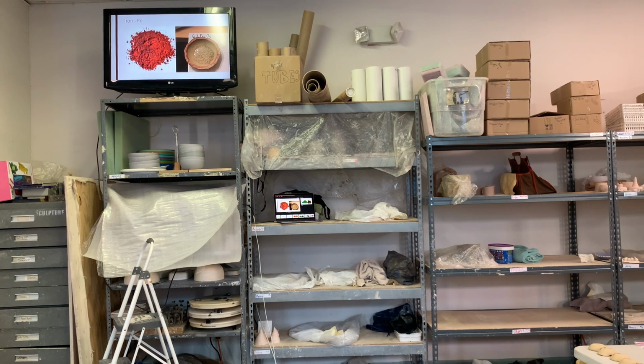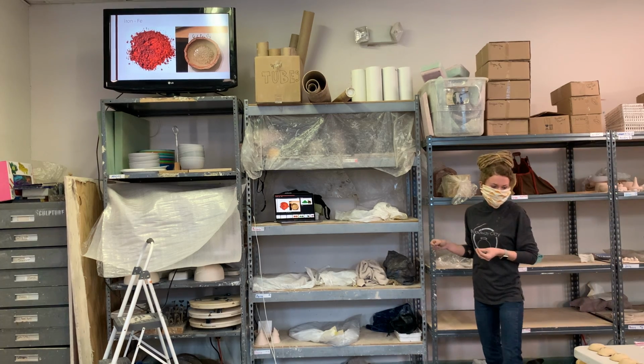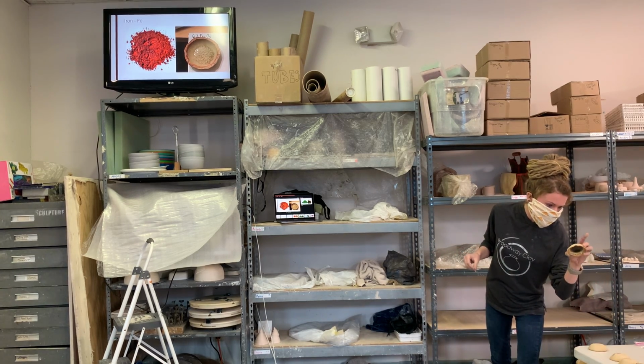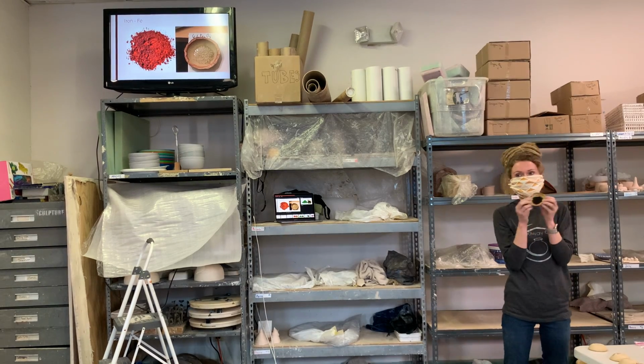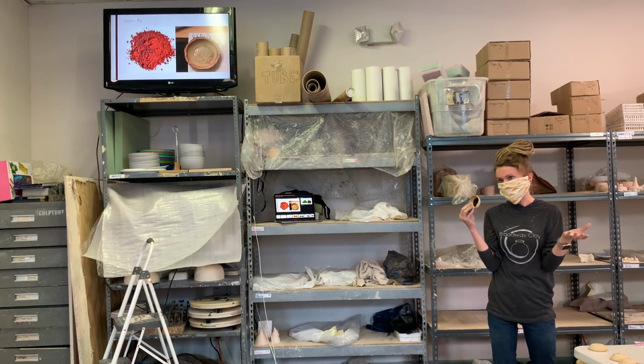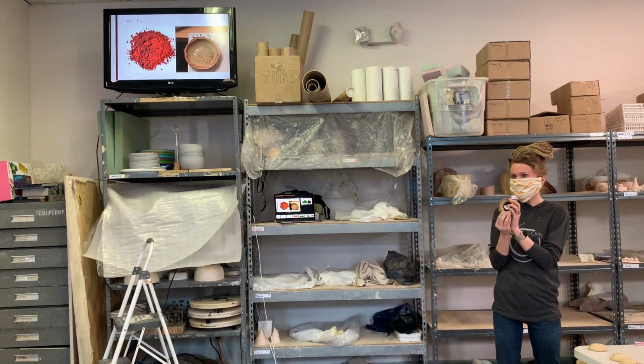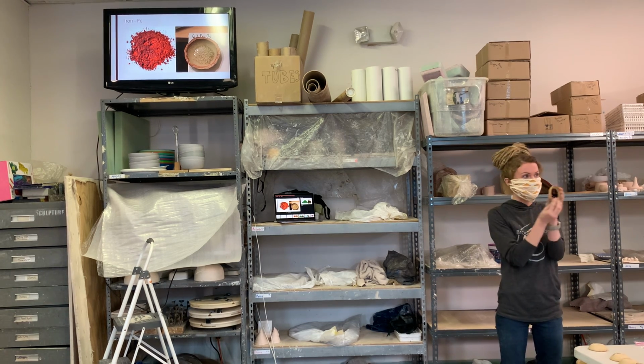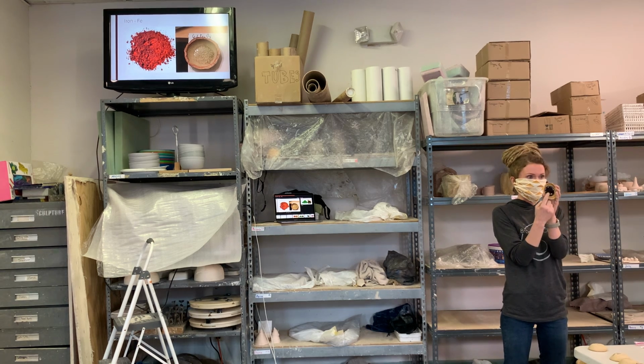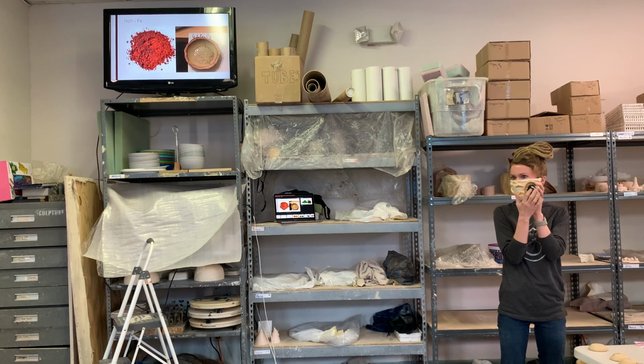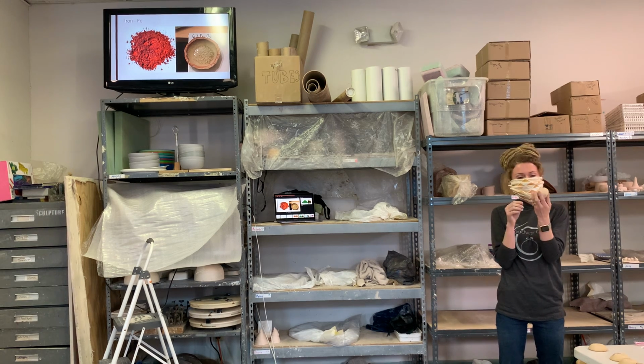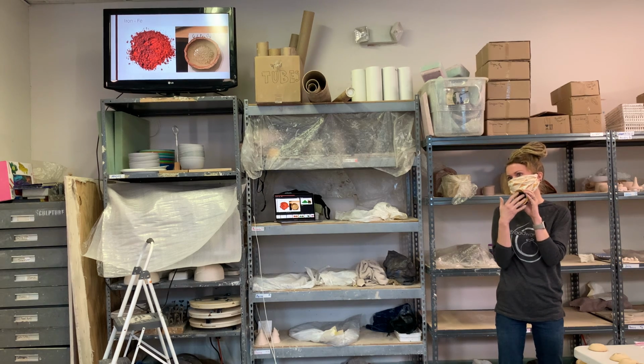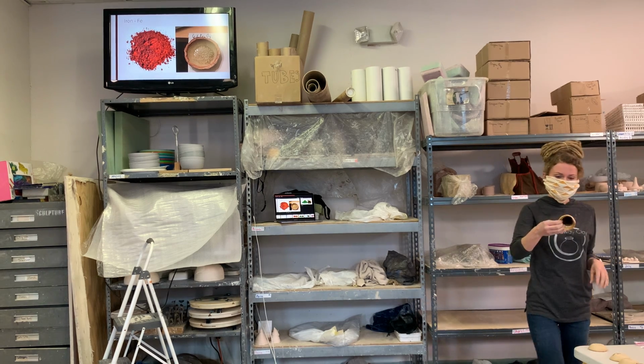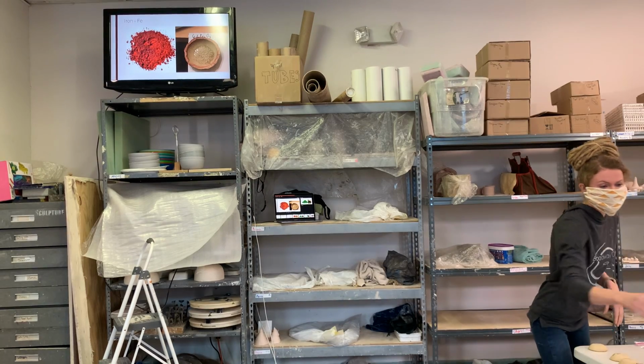The black irons give you what colors? It's all going to be like the brown, the yellow irons. And this is iron oxide and 3134. So frit by itself is just glass. I put frit in here, heat it up to cone 5 and put some of the iron in it. Now we are adding the stabilizer so it doesn't run off the pot. If I were to put this right on the pot, it would run off. And the glass former, because if you look close, it's crazing. So it needs that glass former to fill in those cracks so it's a solid, stable piece of glass. So that's iron in the flux that we're using.